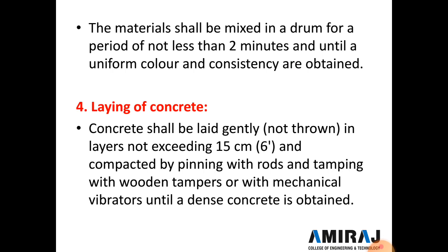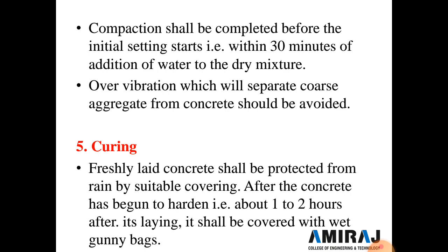Next point is laying. In the laying, the concrete shall be laid gently in layers not exceeding 15 centimeter, and compacted by pinning with a rod and tamping with a wooden tamper or by vibrator, until dense concrete is obtained. And compaction shall be completed before the initial setting starts. So within 30 minutes of addition of water to the dry mixture, we complete the compaction work. And over vibration, which separates the coarse aggregate from the concrete, should be avoided.